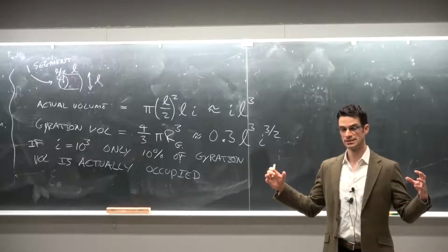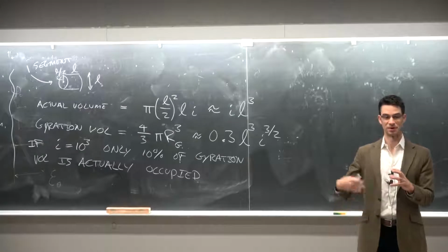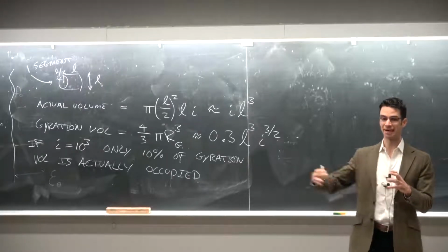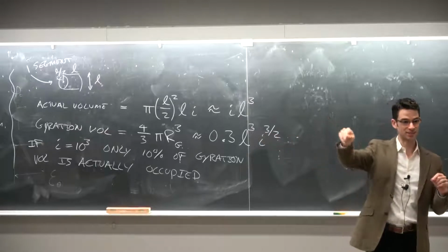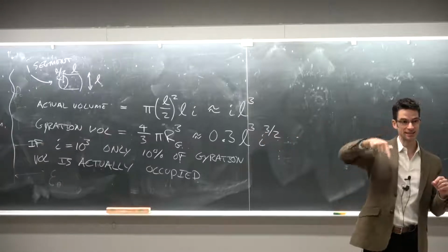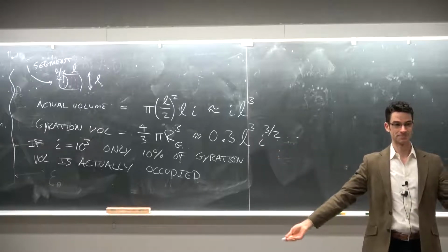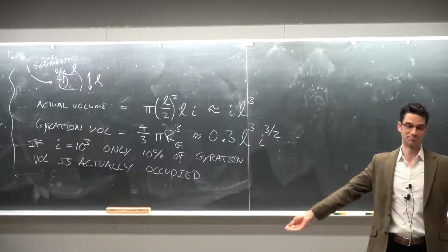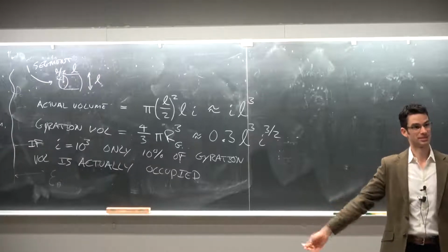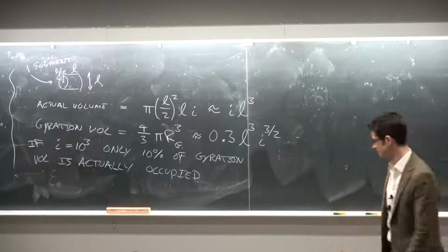Unless it favors itself. It favors itself, so it's going to shrink. Now, say we have polystyrene, which is a polyolefin, this zigzag CH2 chain with some pendant benzene rings on it, and we put it in benzene. Is that a good solvent for that polymer? Yeah, because it's sort of like polystyrene, so it might tend to relax a little bit and expand.